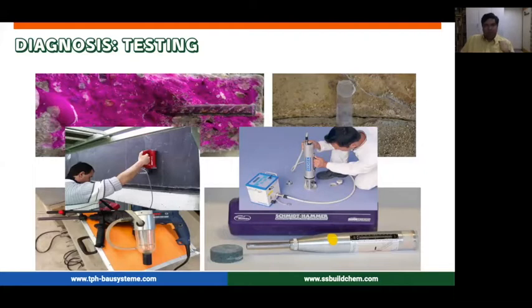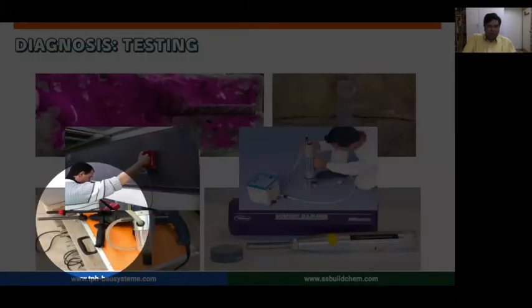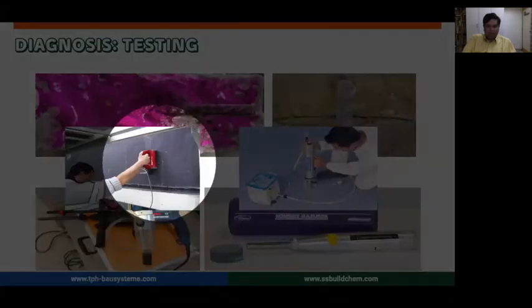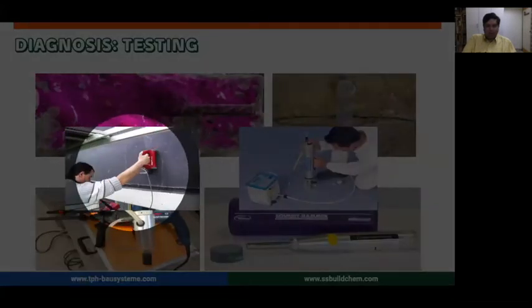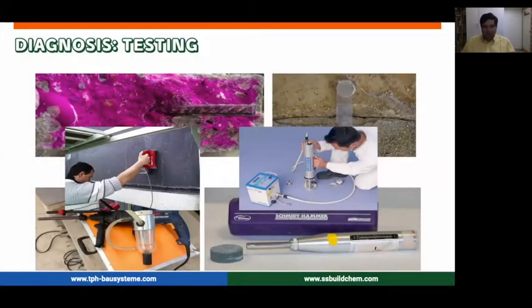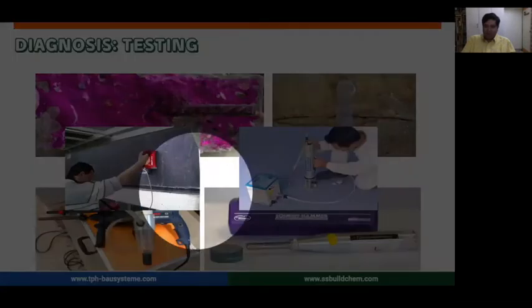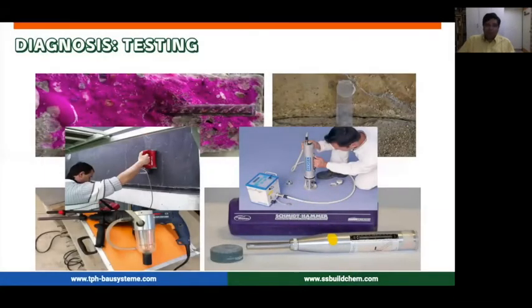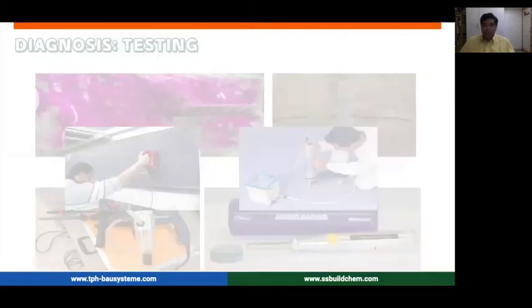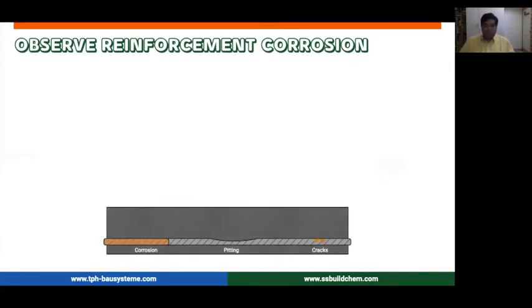So even basic things like a phenolphthalein test, crack movement, then you have maybe a test like a pull-off test for strength. The one here on the left-hand corner is for getting small samples to test the chloride profile and chemical makeup of the concrete. Then you've got other non-destructive testing based on, say, impact echo, or UPV and so on. And then you have a Schmidt hammer, something that can just tell you whether the surface is good or not. So this kind of testing is very important in the whole diagnosis part of it.